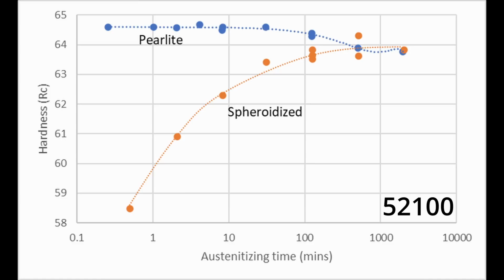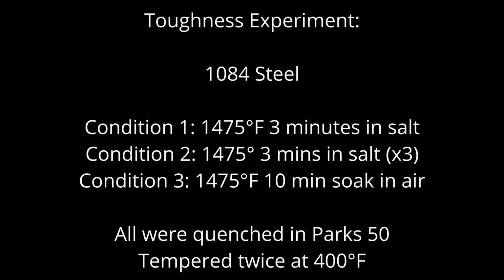For a lot of cases, I actually prefer a spheroidized structure, maybe a little finer than what you get with a factory annealed condition, but with a spheroidized structure, you can control your final hardness and your final properties, whereas with a pearlite structure or a martensite starting structure, you can't really control things. It just immediately dissolves everything and you get the same properties. But I wanted to point out that in certain cases, it is less sensitive to the soak time. Okay.